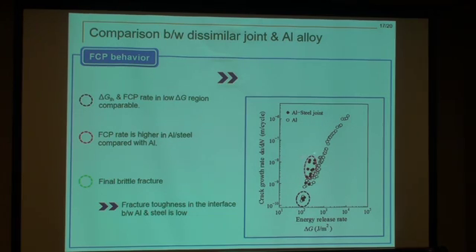But in the middle range of delta G, the crack propagation rate in the dissimilar welds becomes a little bit higher than the aluminum alloy, and after that, it fractured in a greater manner. So the brittleness, the fracture toughness of the intermediate compounds in the interface in the dissimilar joint is quite lower than the aluminum alloy itself.